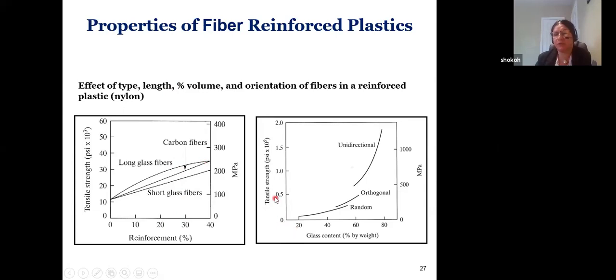Now on the orientation part, tensile strength will change based on whether it's random, meaning no orientation. If I have no orientation, my matrix is full of different fibers going in different directions, and the tensile strength is very low. If I change the configuration to give some angle to the fibers, I get better improvement. And if I have unidirectional, meaning all fibers align in one direction inside the matrix, it gives me the highest. So it's the same material, same fibers, but very different results. How you make it gives you very different mechanical properties.